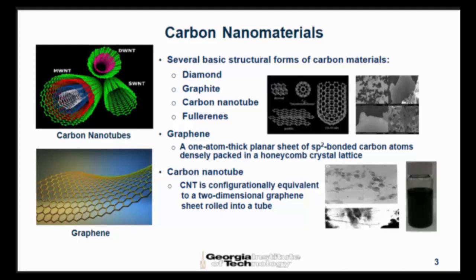So the way we are making these materials is we make flakes or nanotubes using the appropriate chemistry, and then we make a solvent of that. We sonicate it to get rid of agglomerates, and we deposit this solvent on a tiny area for the sensor using inkjet printing or spray coating or drop casting, etc.